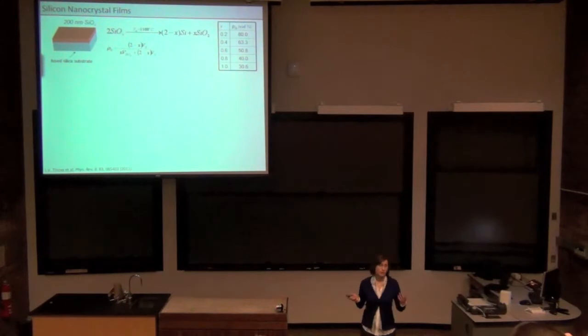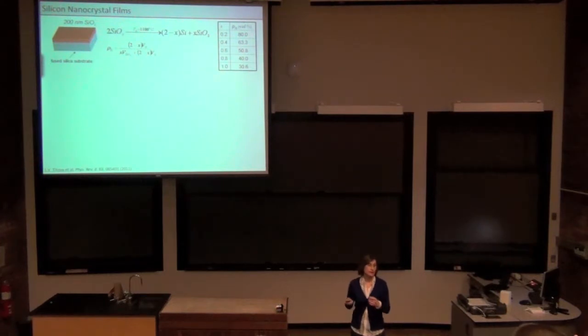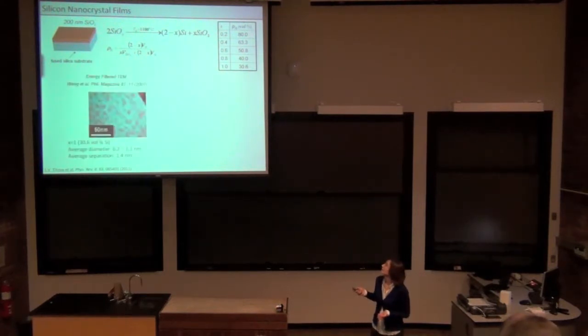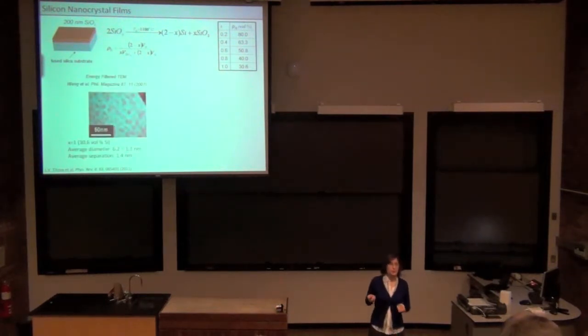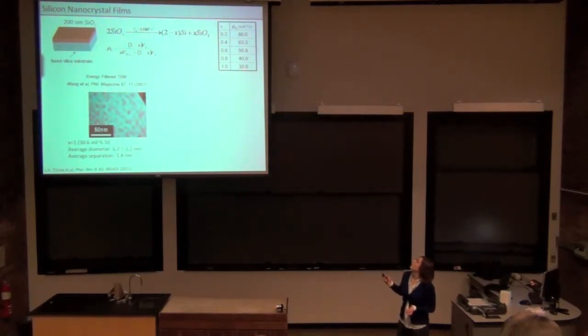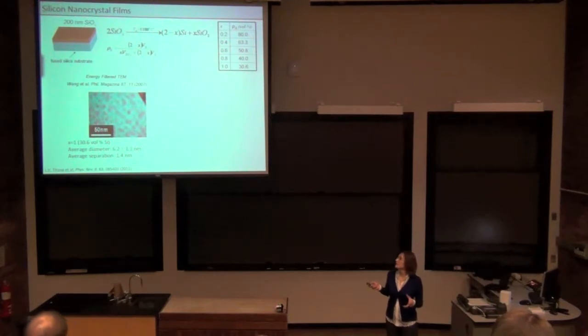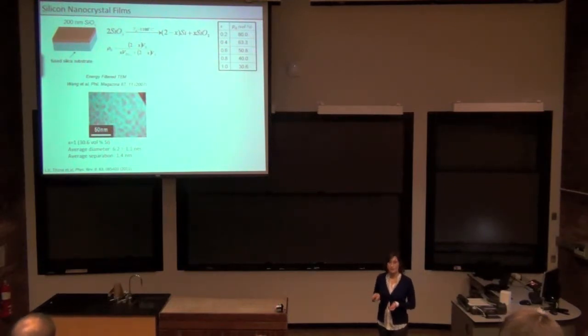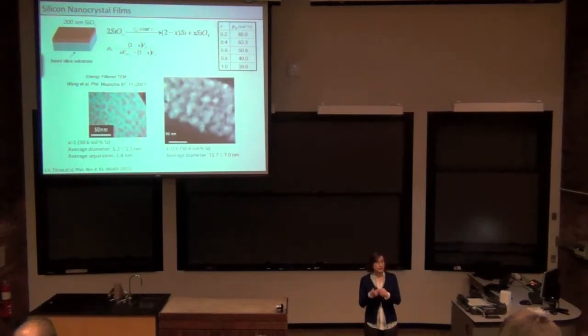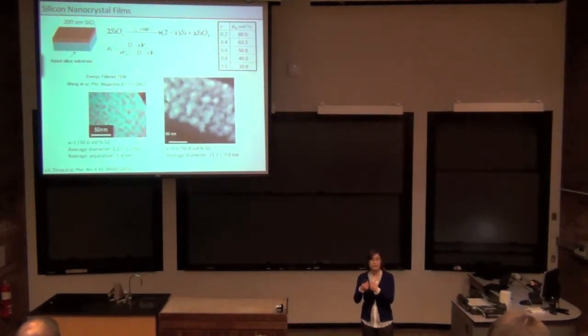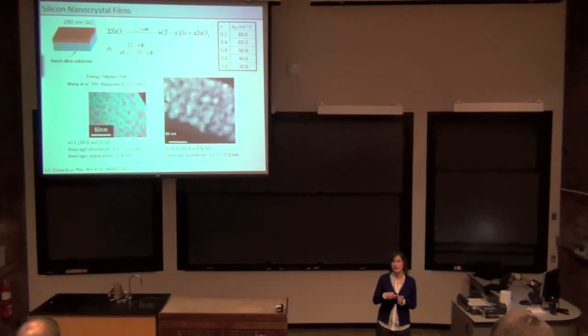They grow a silicon-rich oxide, and then they anneal it, it phase segregates, and forms these very nice enclosed nanocrystals. From TEM measurements, we know that at one end of the spectrum, 30%, the nanocrystals are about 6 nanometers in diameter. They're also quite well separated. Then as you increase the filling fraction, of course, they start to touch, they start coalescing, you start getting some of these pathways forming.